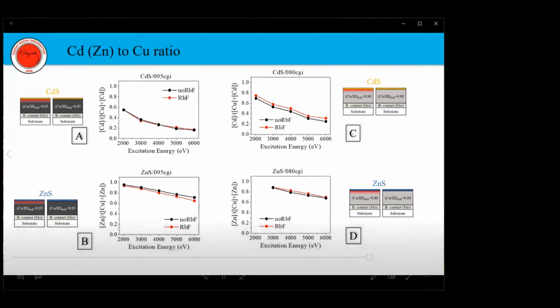Cadmium diffusion is even enhanced by the application of RbF PDT. This can be seen as a slight upward shift in figure C. This is explained by the formation of a rubidium-containing layer on top of the absorber and an ion exchange mechanism between rubidium and cadmium in that layer. Since the thickness of the rubidium-containing layer is proportional to the concentration of copper vacancies, the effect is most visible in the copper-rich sample in figure A.